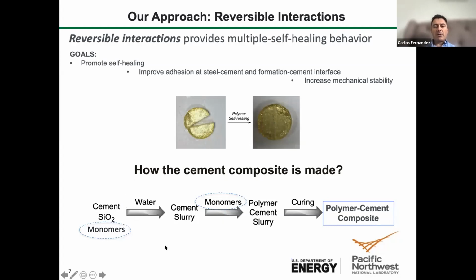We talked about this in the previous talk, so I will go very fast. Basically, you either have monomers as a powder, and a cross-linker also, and you add it and you mix, you make a solid solution of the cement, the pozzolanic material, and the polymer precursors. And then that slurry will cure and form the cement hydrates. At the same time, we will cross-link and polymerize the polymer, forming a kind of mesh of cross-linked polymer across the entire matrix. So the polymer will be homogeneously distributed in the entire matrix.